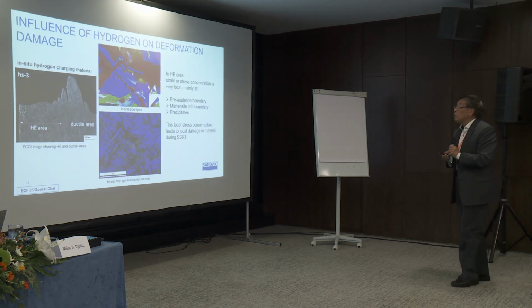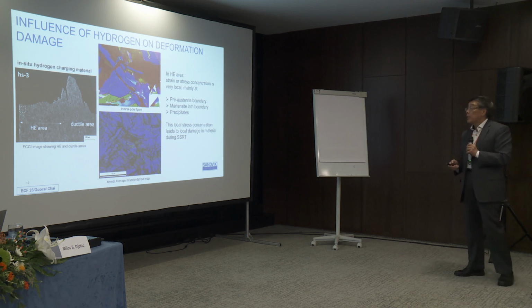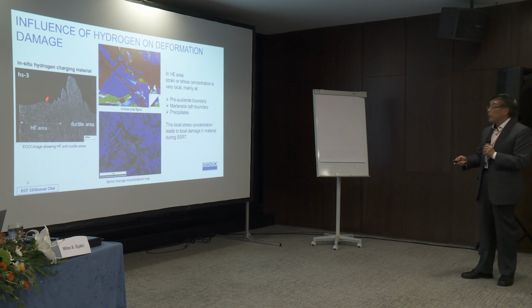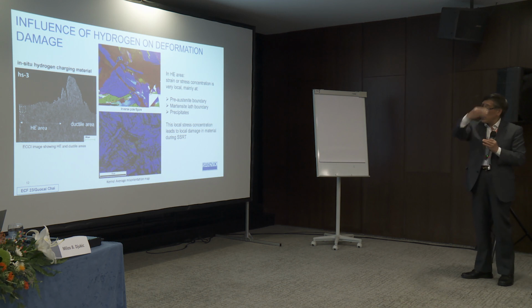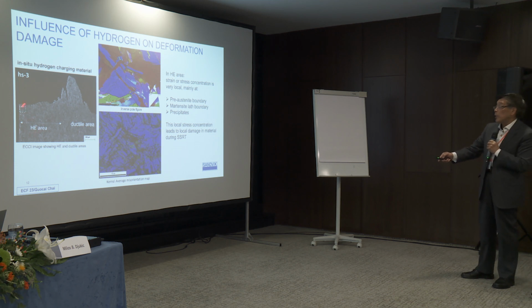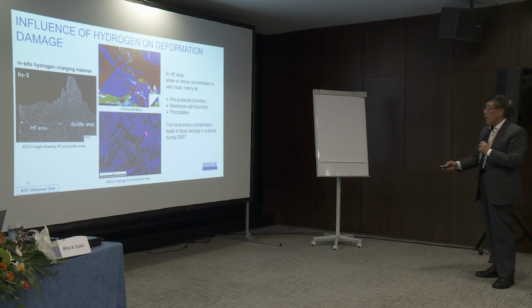Now we want to study the mechanism. So we look at the cross section. We can find that this area is mainly the hydrogen embrittlement area. This is the ductile area. So we can take a small area with EBSD. We can find the stress concentration, mainly at some inclusions, austenitic phase or martensitic laths.